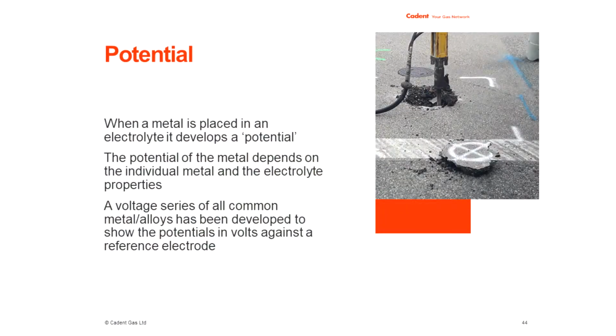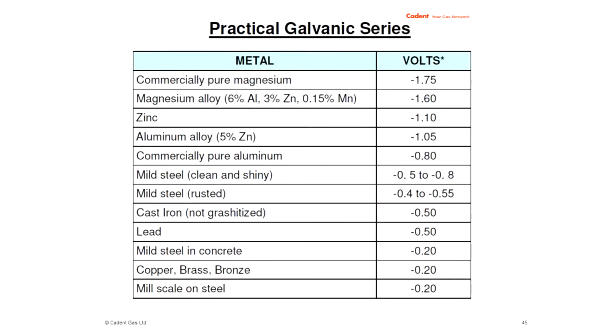So when you immerse a metal in an electrolyte, it develops a potential. The potential is basically the driving voltage that metal has. And over years, this has been put into a table, and it is known as the galvanic series. So if you just have a look at the top of the table there, commercially pure magnesium has a driving voltage of minus 1.75 volts. And with it having the highest driving voltage, that is what we tend to use for our sacrificial anodes.